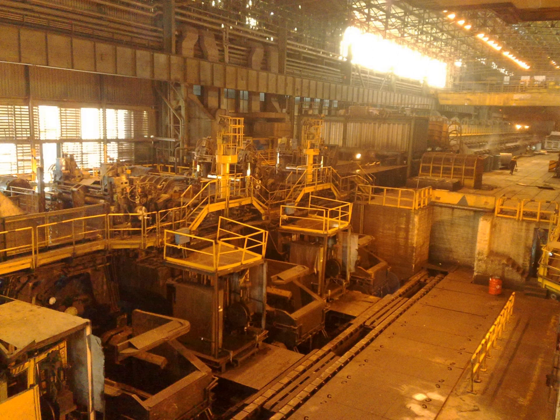The steel making and continuous casting plant has 8 electric arc furnaces receiving sponge iron and other additives. They are melted with about 15% scrap in the furnace, which has a capacity of 180 to 200 tons. The plant also has 4 ladle furnaces, to be increased to 8 in the current revamping, and 1 degassing vessel, to be doubled, used to adjust the final chemical mix and purity, as well as adjusting casting temperature.